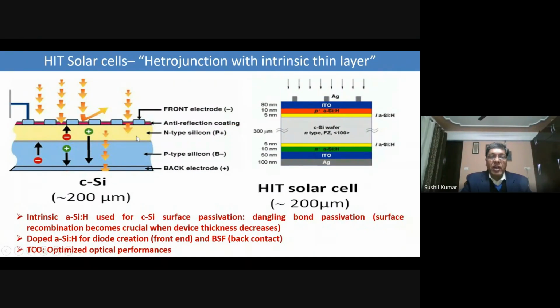This is a conventional cell, as I already explained. Here in this HIT solar cell, HIT stands for heterojunction with intrinsic thin layer. The intrinsic thin layer is basically amorphous silicon. If you see the crystalline silicon, N-type FZ grown 100, this is the parameter for the silicon wafer they have used. 300 micron is given here, but this technology now uses less than 200. Even some industries are working with 180 or 150 micron. You have an intrinsic amorphous silicon here. If you see from the front side and the bottom side both, then P plus amorphous silicon.